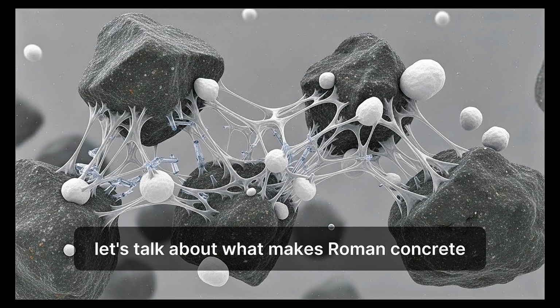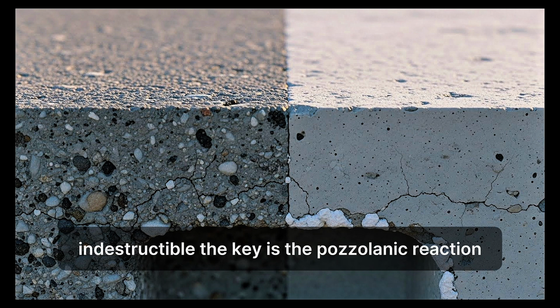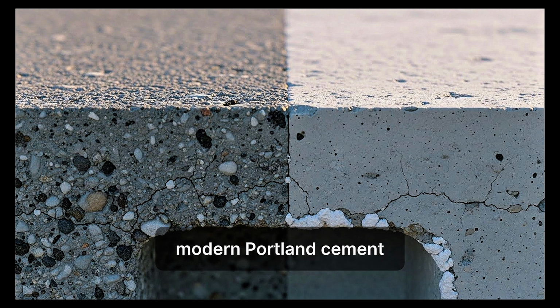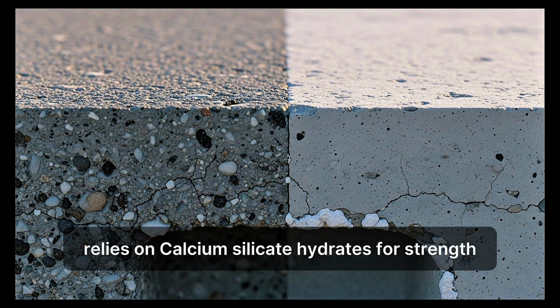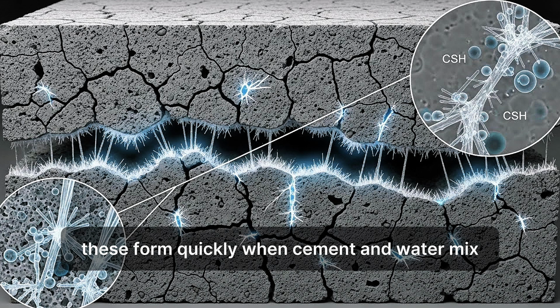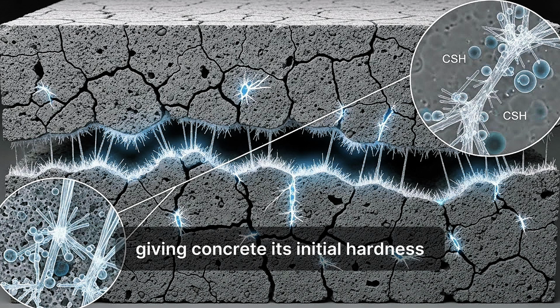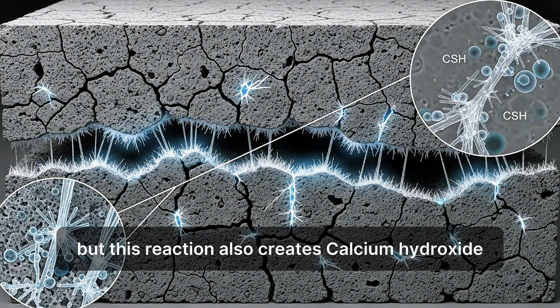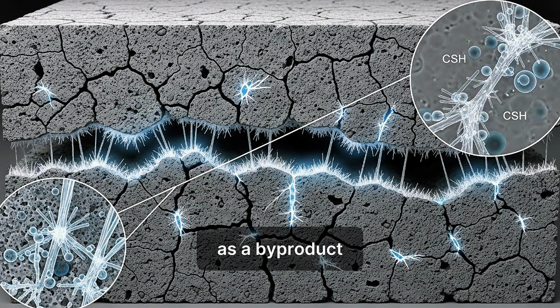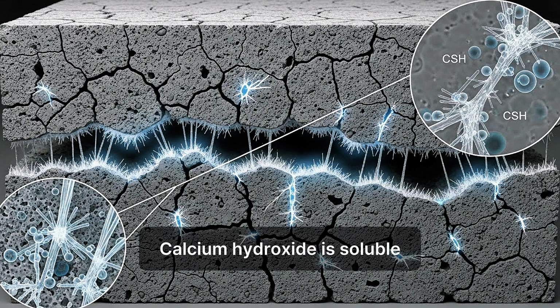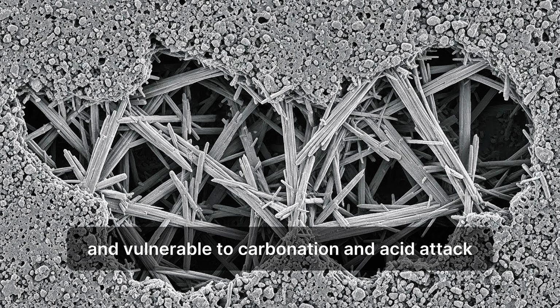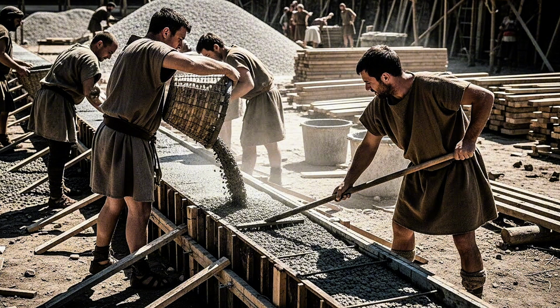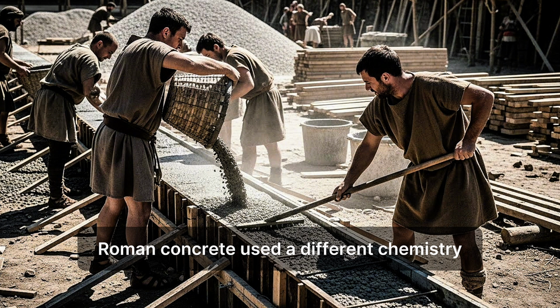Let's talk about what makes Roman concrete indestructible. The key is the pozzolanic reaction. Modern Portland cement relies on calcium silicate hydrates for strength. These form quickly when cement and water mix, giving concrete its initial hardness. But this reaction also creates calcium hydroxide as a byproduct. Calcium hydroxide is soluble and vulnerable to carbonation and acid attack. It's the weak link. Roman concrete used a different chemistry.